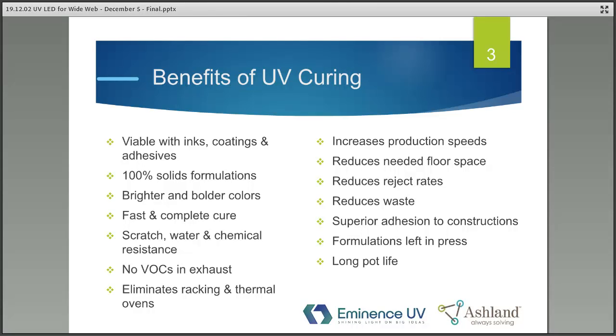It increases production speed. You can go quite fast with UV curing. It reduces the needed floor space. These lamps are quite tiny in comparison to a thermal oven or an infrared oven. You can get some really great yields with reduced reject rates because the process is very repeatable and very consistent. And because you're using everything in the ink, coating, or adhesive, there's less waste, because again, you're not flashing off what you're not using. Everything stays in the tray, so you don't have to remove things when you turn the press off. You can leave it because it's not going to cure unless it's exposed to the UV light.